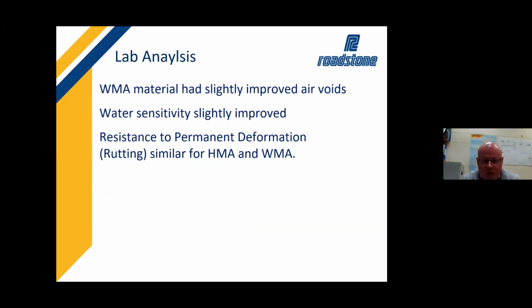We did take samples from the actual production run of the AC14. And what we found was that we got similar air voids for the warm mix materials as we did for the standard materials. No real difference between them. The water sensitivity test that was carried out on both sets was slightly improved for the warm mix materials. That would be something that in the past we've seen and been told can happen. The warm mix additive, because of its nature, will actually help the bitumens improve their binder adhesion, but also give a better coating with the material.